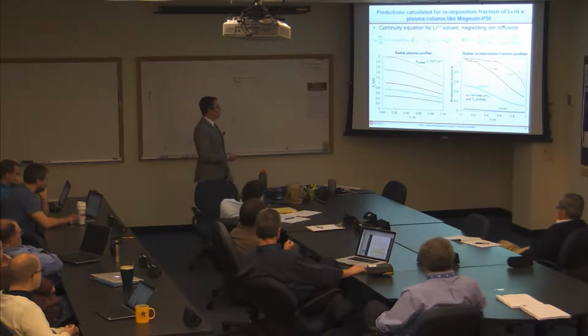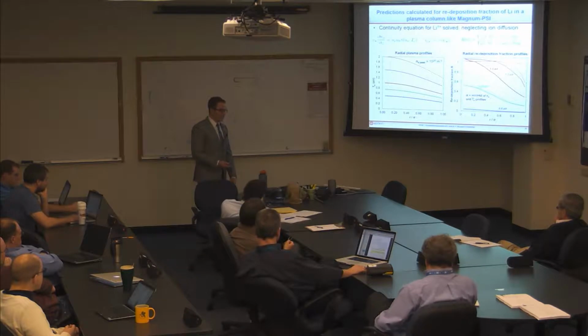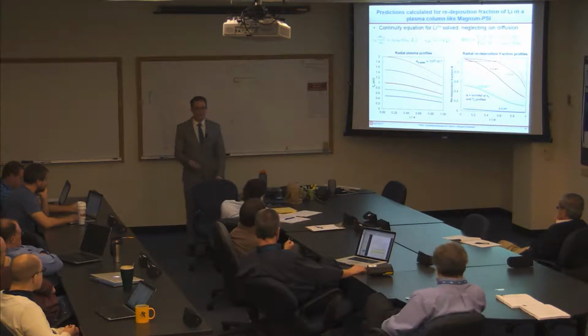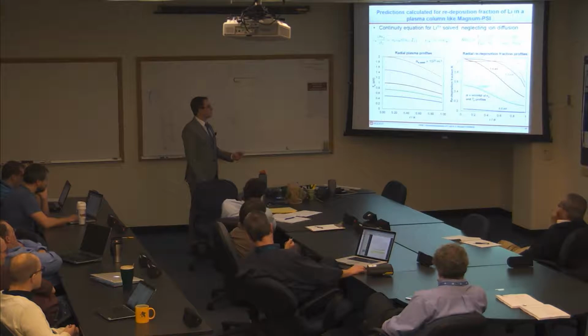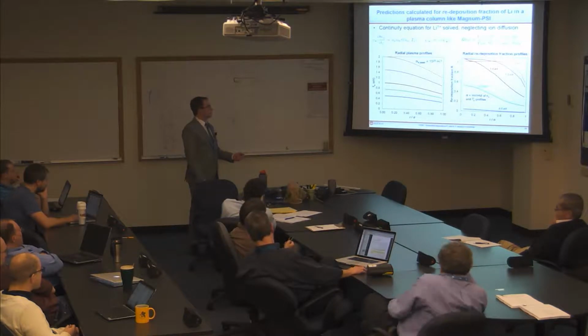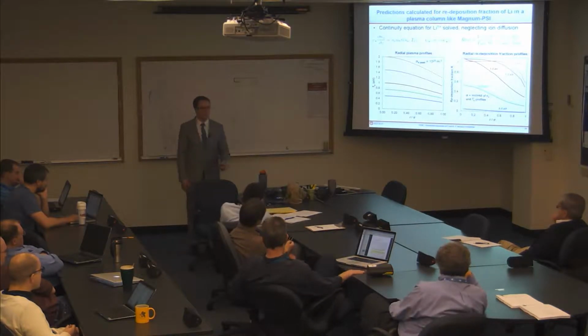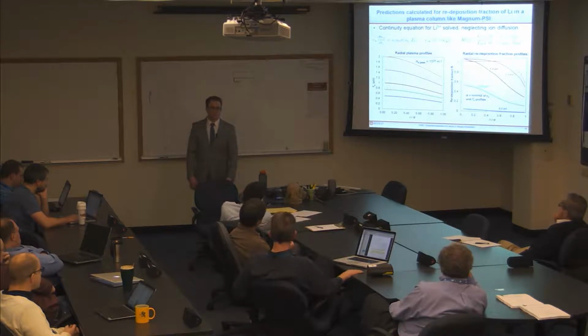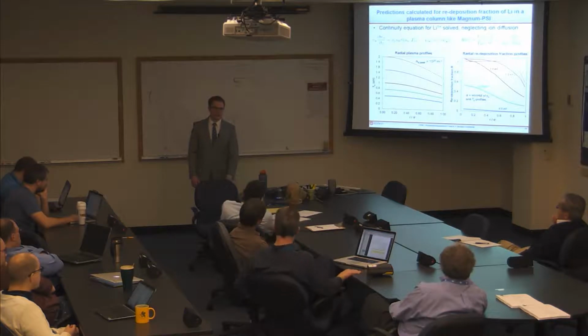And we are assuming that the lithium atoms are quickly being thermalized by the plasma that is streaming along the field lines to the surface. And so it quickly obtains the ion sound speed velocity towards the surface. What's the process by which that thermalization takes place? Coulomb collisions. With what species? Deuterium plus and lithium plus. Not the electrons?